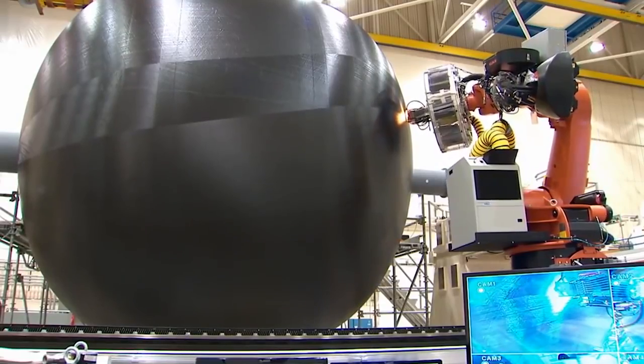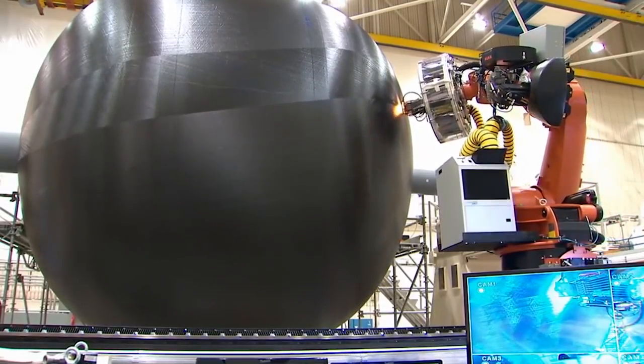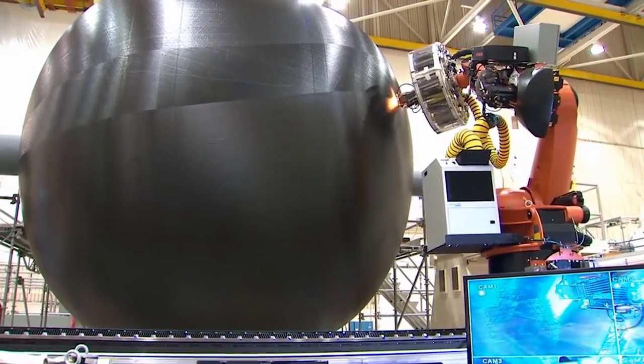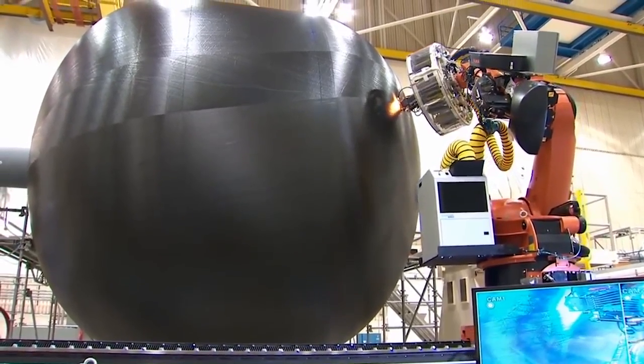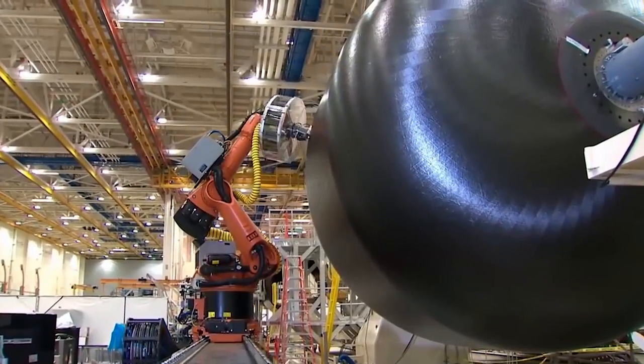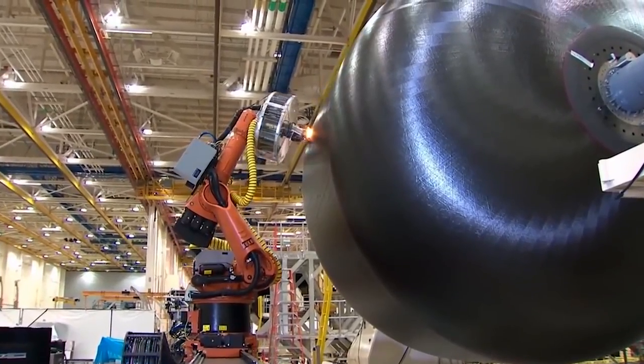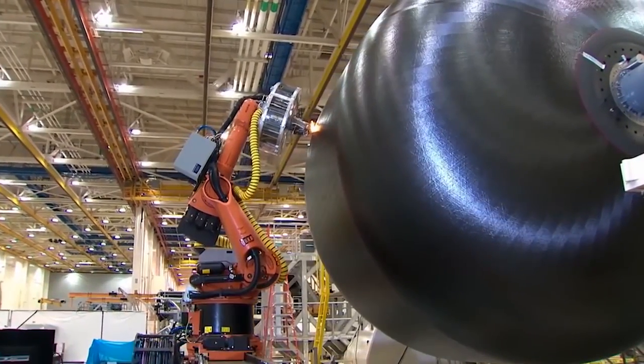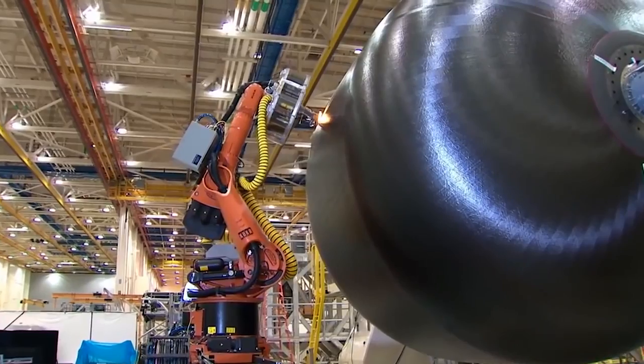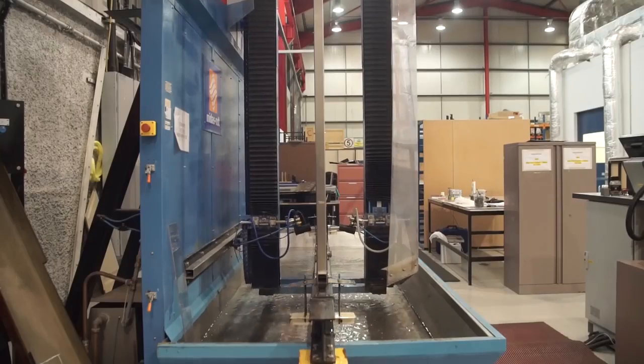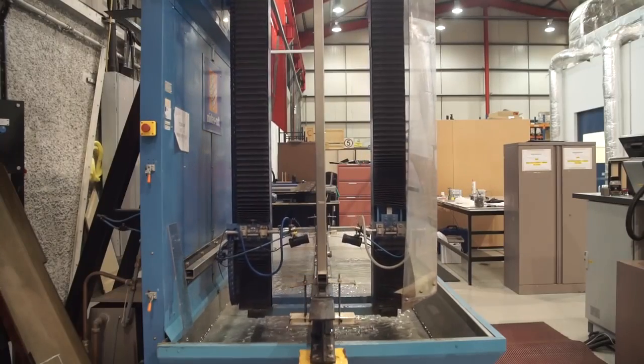But it's very hard to create quality parts with this method, as the pressure of the autoclave is essential for removing voids in the resin. And this is such a huge concern for composite manufacturers that parts are often scanned with ultrasound technology to check that the resin has cured with a tolerable amount of microvoids. This machine sends ultrasound into the part through a jet of water and detects the voids in the material.